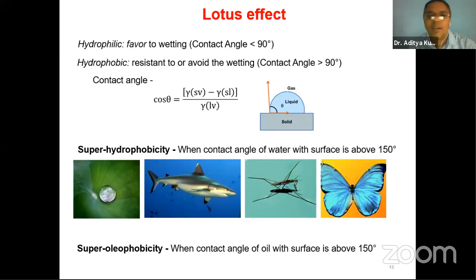So we all are engineers or educated people. We always see everything with numbers. So you measure hydrophilicity or hydrophobicity in terms of the contact angle. And the contact angle is defined like this: if you make a tangent to the surface at the side of the liquid droplet or water droplet, then the angle it makes with the tangent is the contact angle. And here I start to introduce one word, super-hydrophobicity. Super-hydrophobicity is when this contact angle is more than 150. Hydrophobic is when the contact angle is more than 90. Hydrophilic is when the contact angle is less than 90. And if we talk about oil, we call it super oleophobic when the oil makes a contact angle with the surface of more than 150.